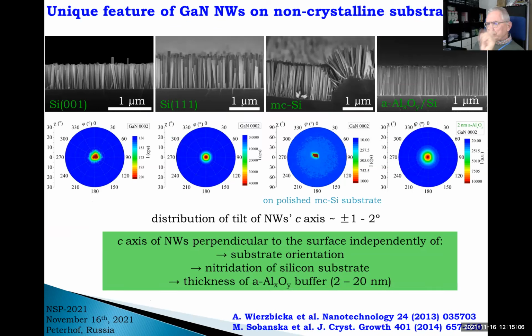Okay, you're asking about twist or tilt? Twist. Okay. Tilt is clear, there are many factors. I see. On aluminum oxide, twist is random, completely random. What we know from our previous work on silicon nitride, on nitridized silicon, is that if we nitridate silicon at low temperatures, the twist is also random. But if we expose the substrate to nitrogen plasma at high temperatures, then the twist is no longer random. There is epitaxial alignment, meaning that in terms of epitaxy, there must be a kind of link between the wire and the substrate.